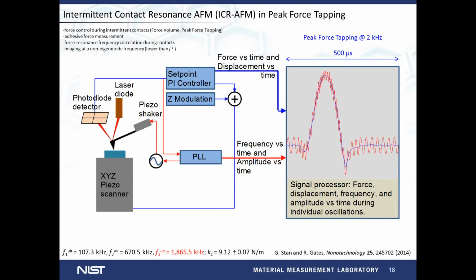So the question is, can we make it faster? And the answer is yes, we can actually implement intermittent contact resonance AFM in PeakForce Tapping. This is because in PeakForce Tapping all the requirements that we mentioned earlier are satisfied: force control during intermittent contacts, DC force measurements, force-resonance frequency correlation during contacts, and imaging at a non-eigenmode frequency. It's important because in tapping mode we don't have these. Tapping mode operates with feedback on amplitude, doesn't provide DC force measurements, and operates at the first eigenmode frequency of the cantilever.